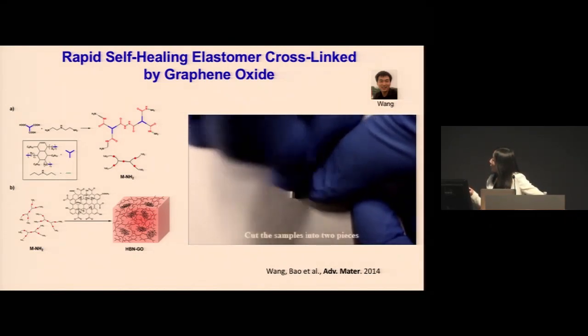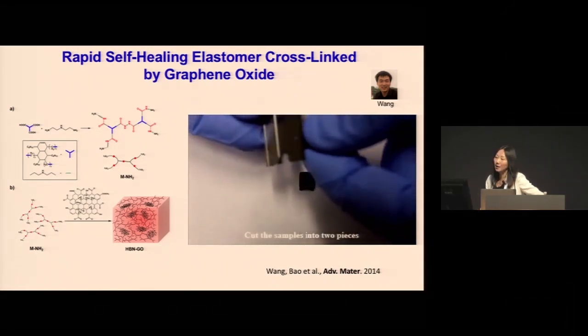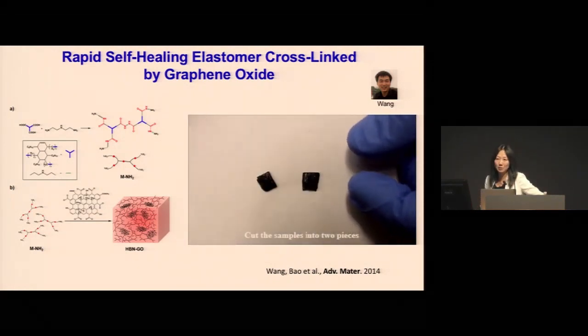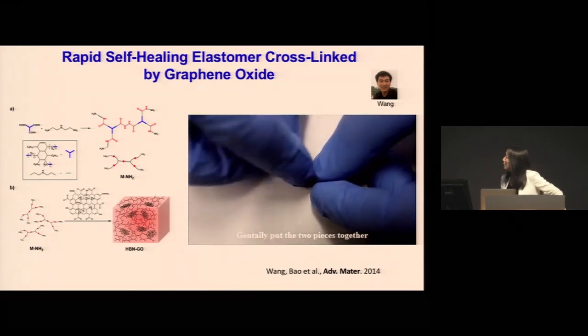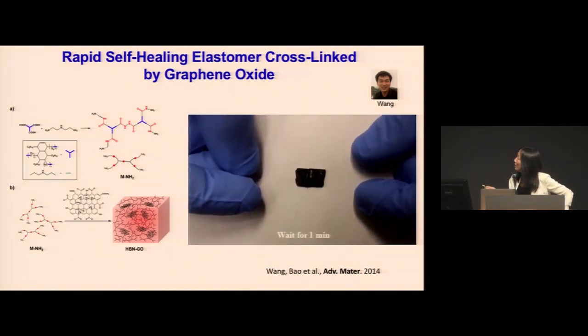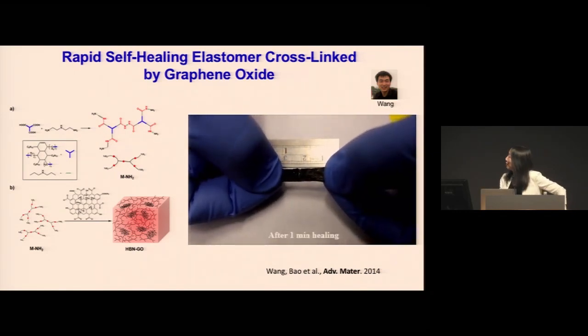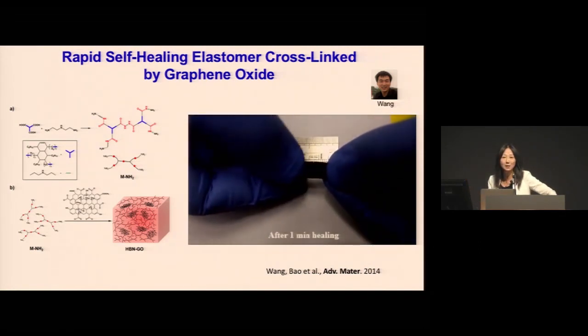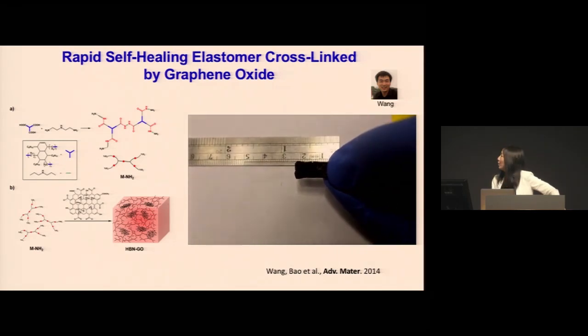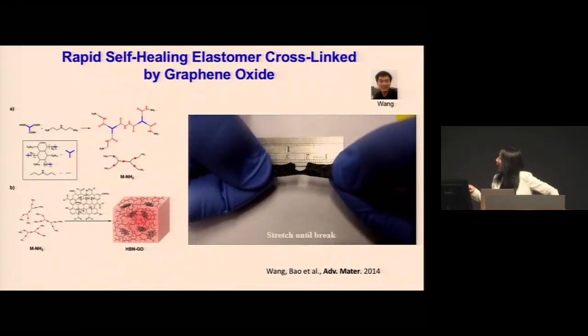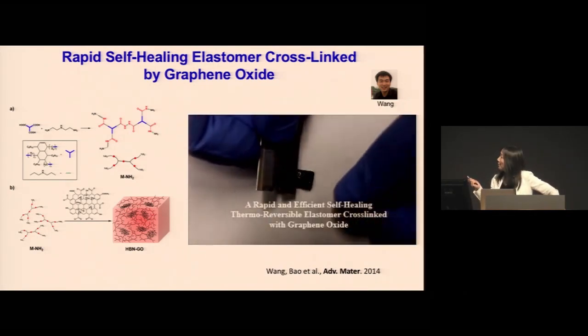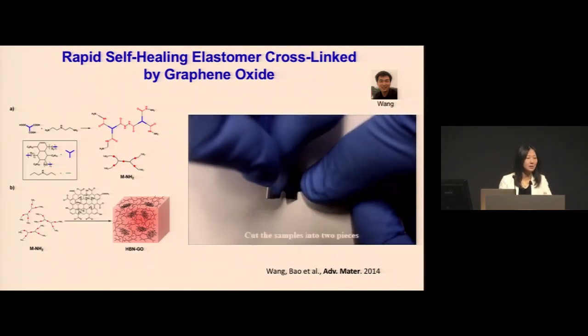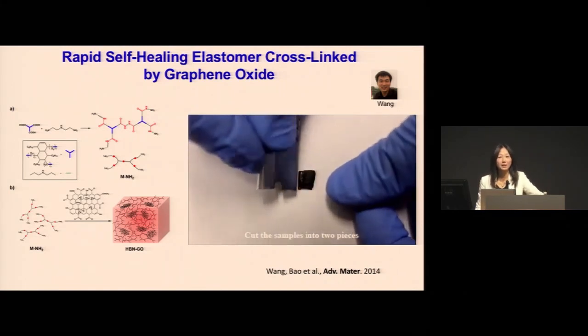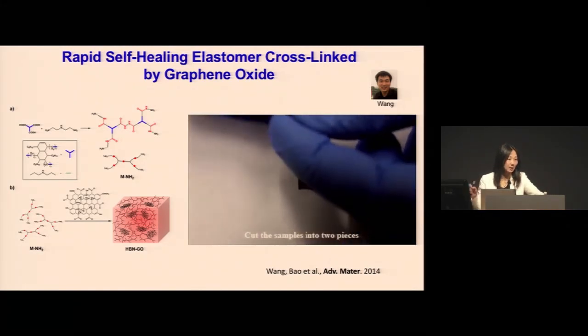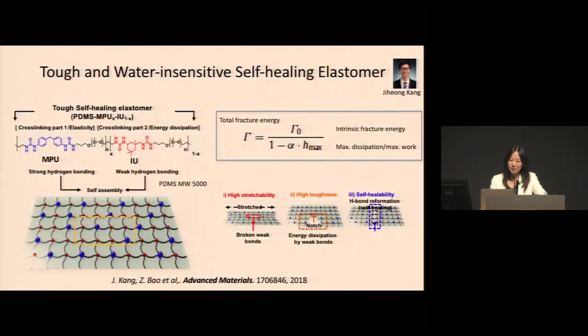So for our second generation material, we used the understanding of trying to balance the amount of covalent bonds versus the amount of dynamic bonds in the material to introduce macro cross-linkers without compromising having a lot of hydrogen bonding. This allows us to make this now elastic material that can heal very quickly, within a minute. Most of the chemical bonds at the interface have already been recovered. But you can see that if there's a defect in this material, along the defective sites is where the crack can propagate and the material can still fail. So that led us to think about additional molecular design that can solve this problem.